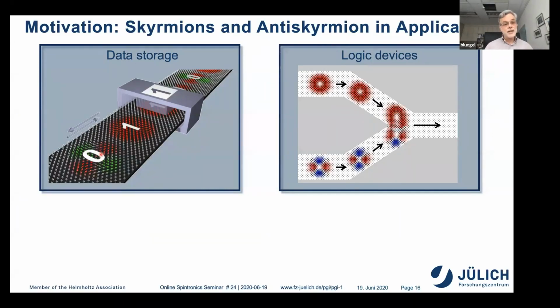This is a great advantage because you don't have to worry anymore about distances of particles. If you have only one particle, it's very important that you have the right distance. Otherwise, you cannot distinguish between a 0 and 1. And at the same time, it offers you the possibility of logic devices. For example, when you have skyrmions and antiskyrmions, you can build logic devices.